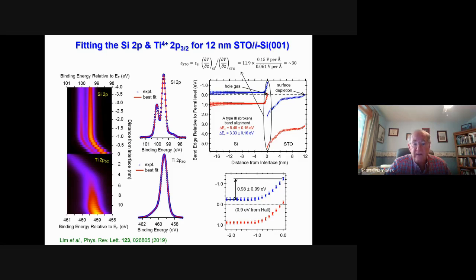Also, we know that the electric displacement needs to be continuous across the interface, and we can use that to solve for the dielectric constant in the STO just by taking the gradient of the potential in the silicon and the STO, and then the dielectric constant of silicon. We get a value of 30, which is right in the ballpark for what other people get when they try to measure dielectric constants for STO grown on silicon. So that's kind of a sanity check.